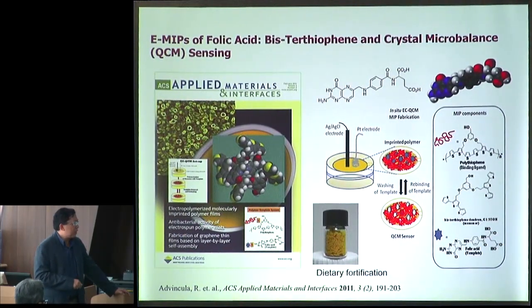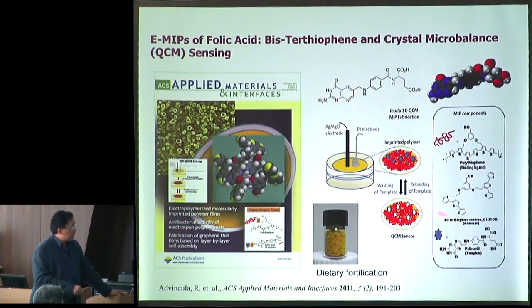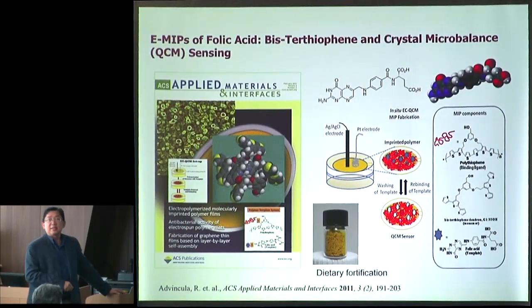So most of those details have been published. Now, we can take folic acid. Folic acid has this structure. We can then complex it with this monomer. And we did the study with 1:3 ratio in terms of the complexation, but the same result. We can get very sensitive quartz crystal microbalance sensors for folic acid using the electropolymerization method.